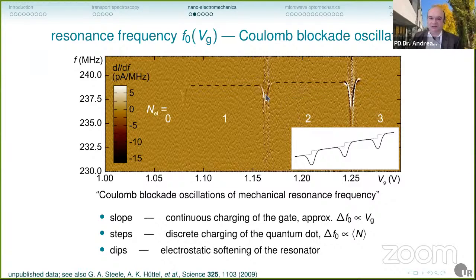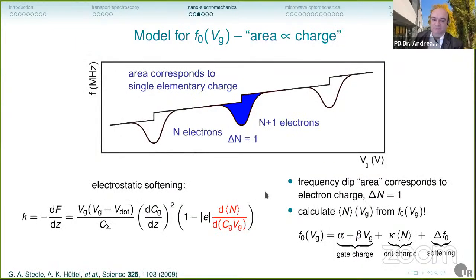It's much easier, actually, to explain this in words than in formulas. Here, the charge on the nanotube can change. So this is the region where the system can adapt in charge. And that means that during one oscillation cycle of the mechanics, when the nanotube comes closer to the gate, the charge can adapt a bit. When the nanotube goes further away from the gate, charge can adapt a little bit. And that leads to an additional force term that counteracts the mechanical restoring force, a negative spring constant contribution, and that leads exactly to this drop in resonance frequency.